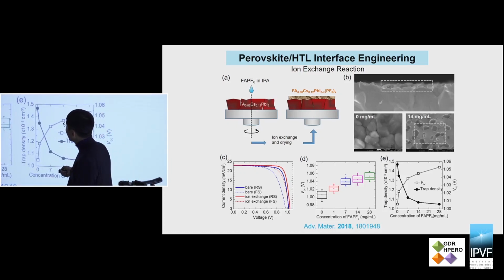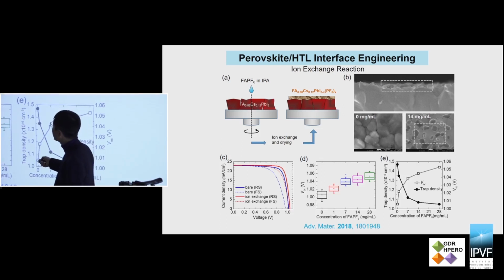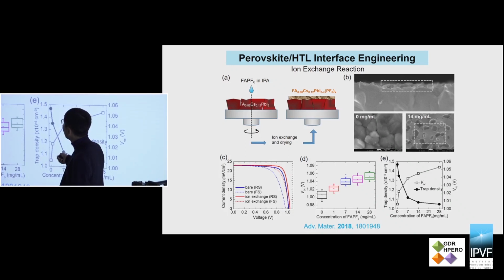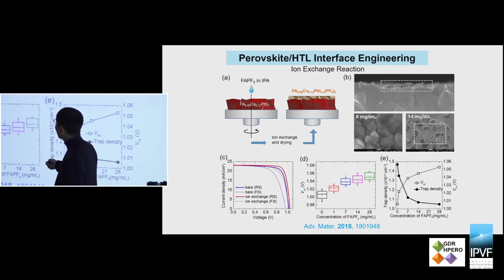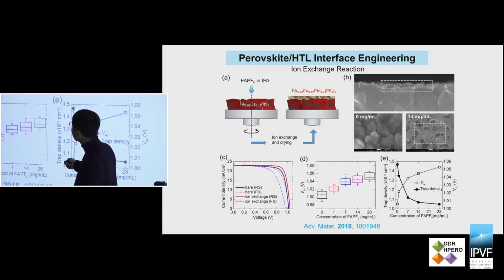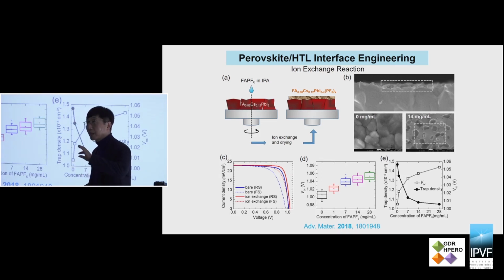For instance, I mentioned the ETL perovskite interfacial engineering, and this is the normal structure, and then the grain boundary engineering, and the third case is the HTL perovskite interfacial engineering. So in that case, usually we use post treatment because once you make the perovskite layer, then the post treatment is an effective way to passivate the grain boundary or the interface with the HTL. Here we have some different approaches using the ion exchange reaction to make some second phase, a different phase on top of the perovskite layer, using this because we know that the surface of the perovskite has the iodide defect.